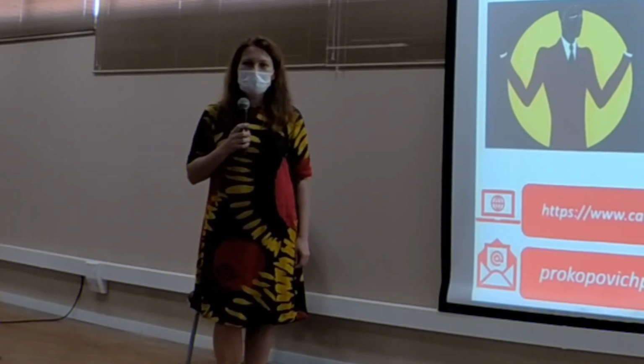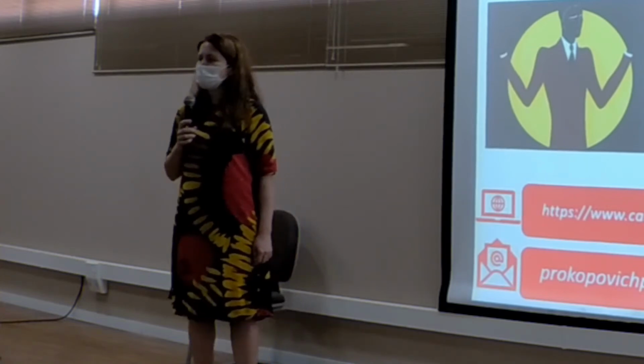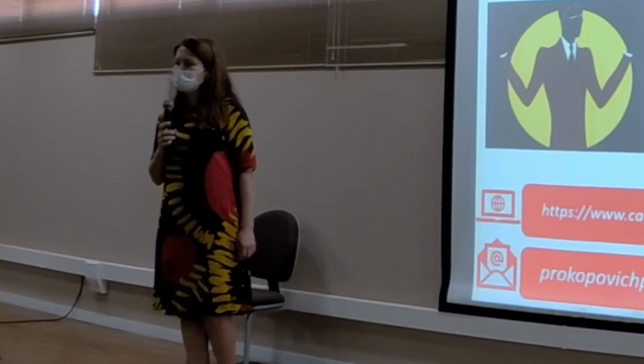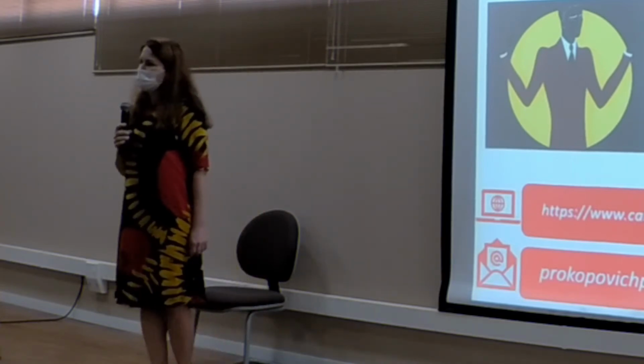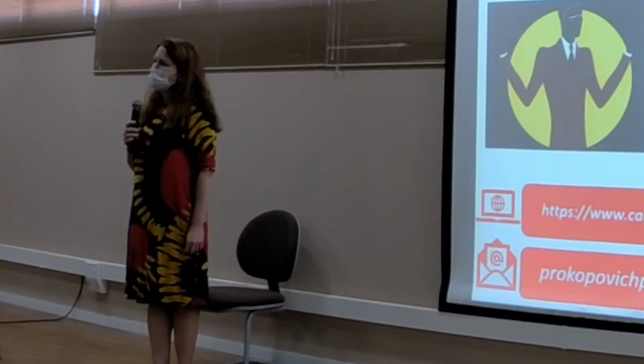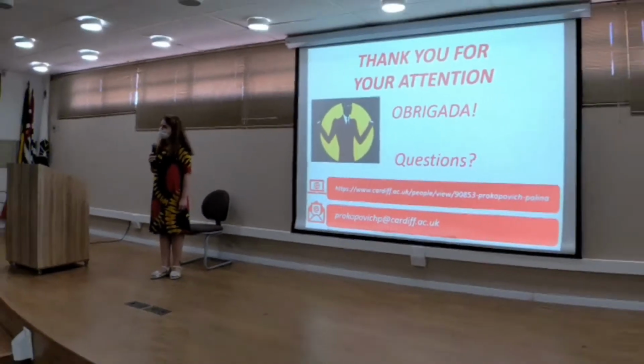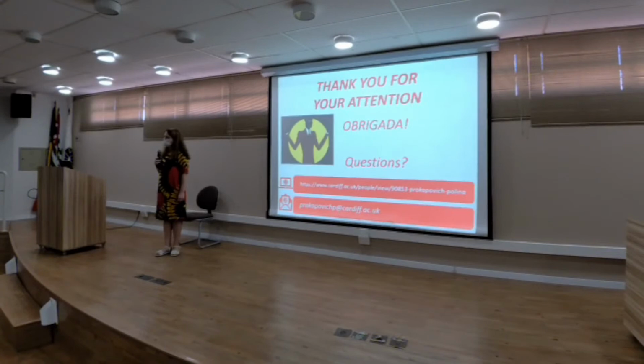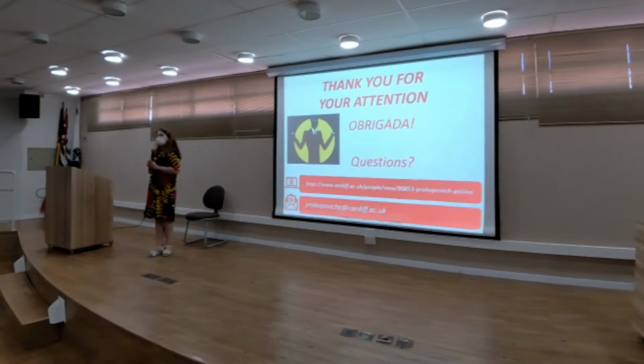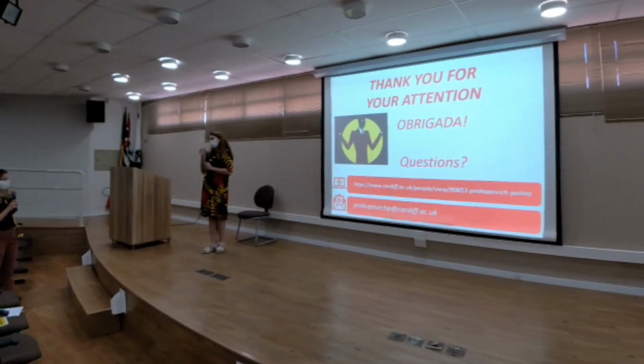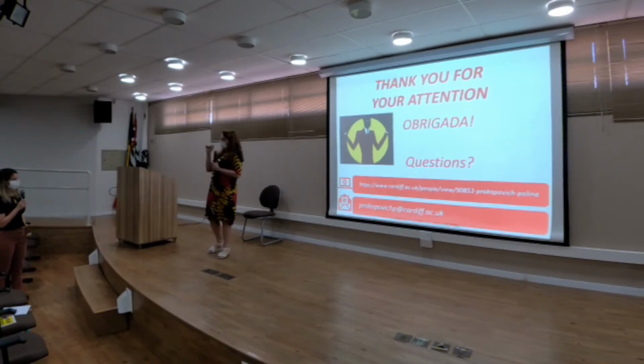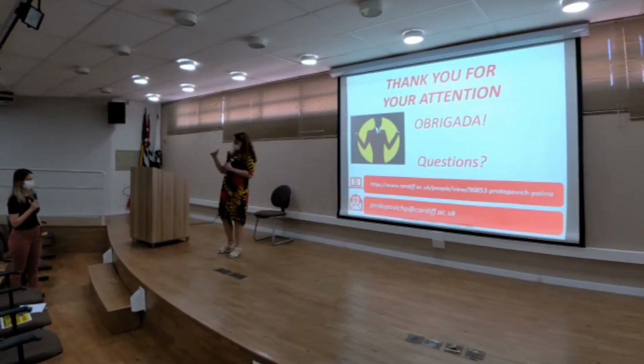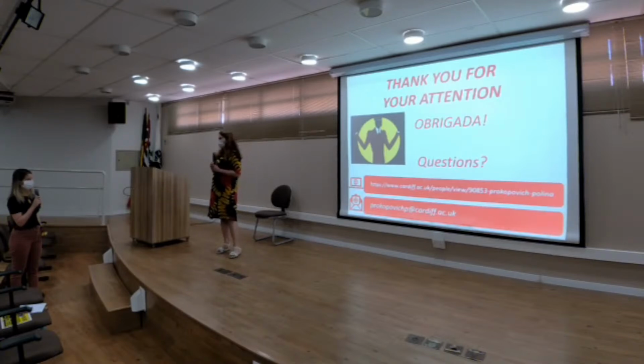Anyone else? No? Polina, I would like to ask you about these nanoparticles. Do you think it's possible to use these nanoparticles for coating implants, for example, instead of using bone cement? Not using nanoparticles for coating implants, but creating a similar layer-by-layer construct on the surface of the implant using the same principle, but instead of coating the particle, you coat the flat surface. Yes, it's possible. We just need to functionalize.